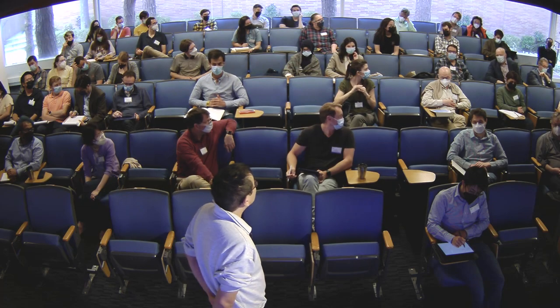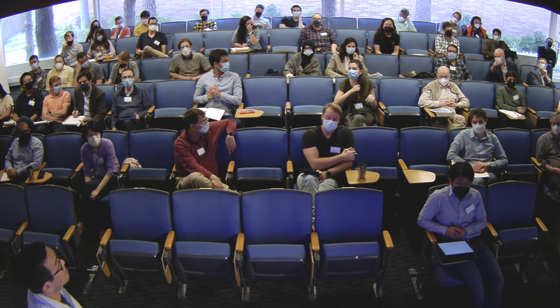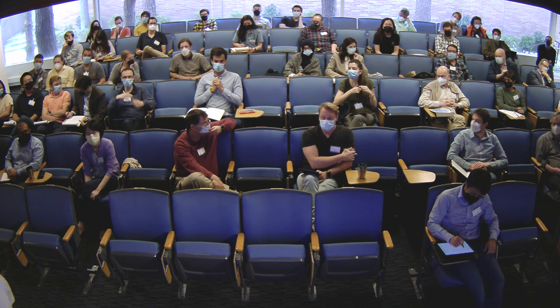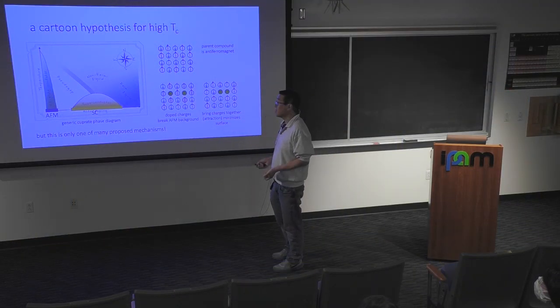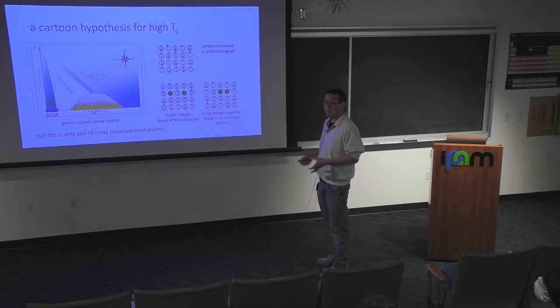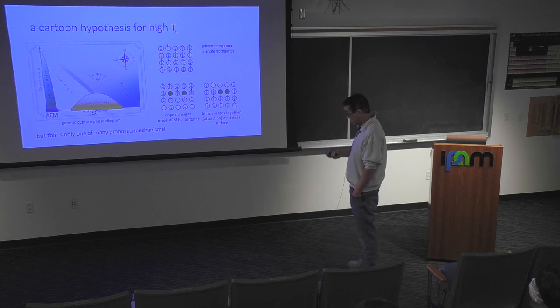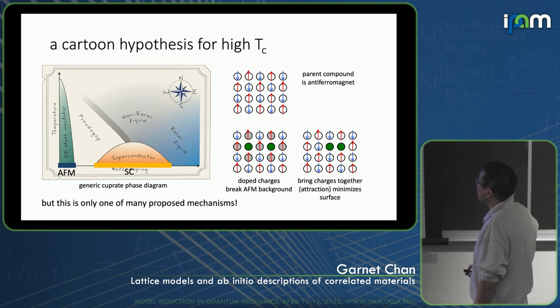My question is, in the usual conventional superconductors, the pairs are of opposite momentum. Yes. So they're not localized in space. Your cartoon, however, suggests that the pairs here are really on neighboring sites next to each other. Yeah, so that's right. In conventional superconductors, the pairing is expected to occur over very long distances. The indications are that in these materials, the pairs are much smaller. I'm sure they're not as small as this. This is just an indication of some way in which an attraction is generated. It's not an indication of what the quantum state actually is. The quantum state could be much larger, but it is considered likely that they're much smaller than in, say, aluminum or lead. So this is just, as I say, a cartoon. It's just one of many cartoons one can draw.